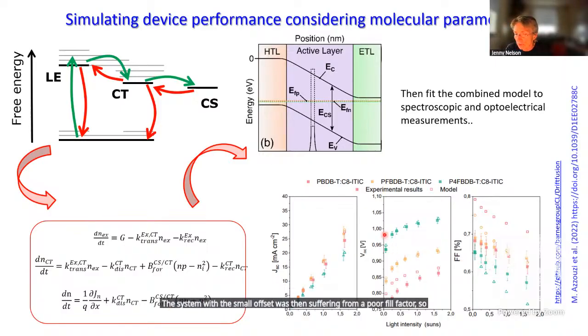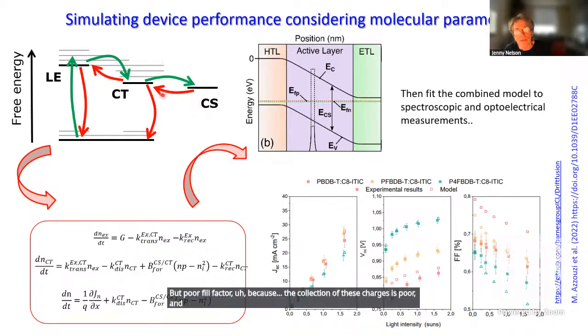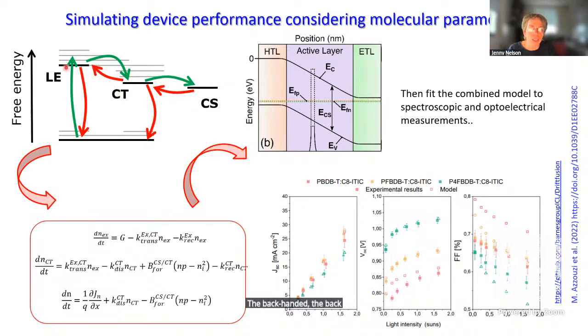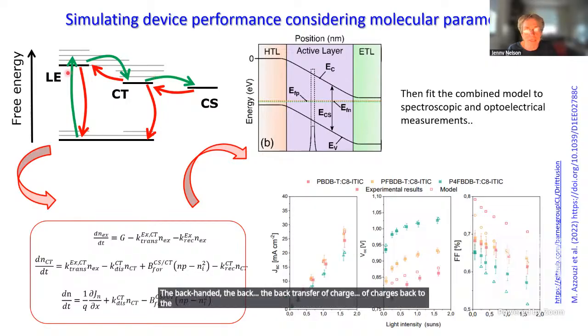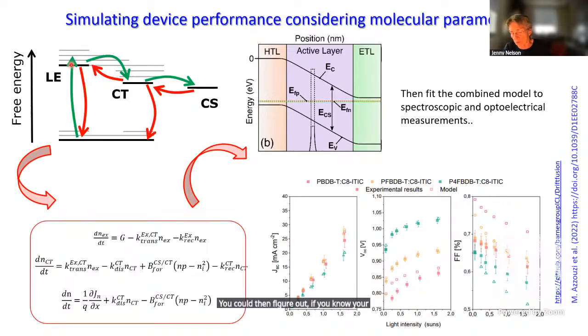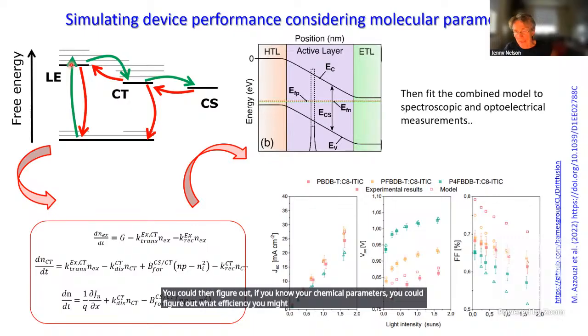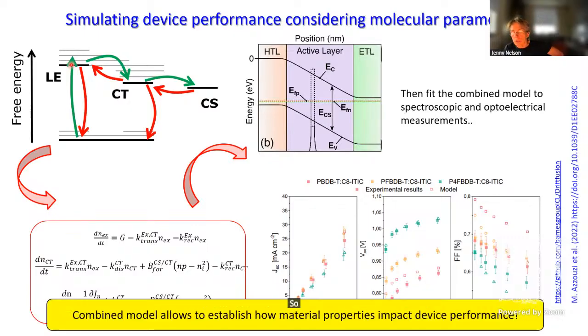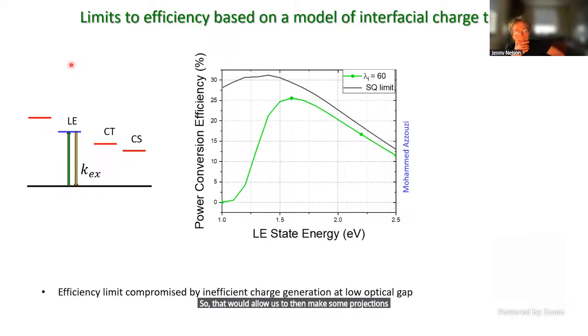So poor, it has high voltage, which is good, but poor fill factor because the collection of these charges is poor. And the collection of the charges is poor because once these offsets become small, the back transfer of charges back to the excited state becomes too efficient, and so you don't collect your charges. So that's kind of then understood, and then from a model like this, if you know your chemical parameters, you could figure out what efficiency you might expect to get. So that would allow us to then make some projections for what might happen.